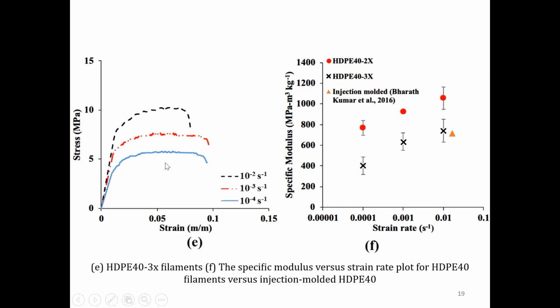What does this mean? You are wearing a shoe, the shoe has a sole, you are standing, there is one rate of loading, that is compression. When you start walking, the same compressive load comes in with a higher rate of loading, and with the same shoe, when you start running, for the same sole, we have a different rate of loading. And this is how soles are manufactured and tested for different rates of loading. And that we also apply for our materials development, so that you get a broad picture of how you can enhance the properties by changing the rate of loading.